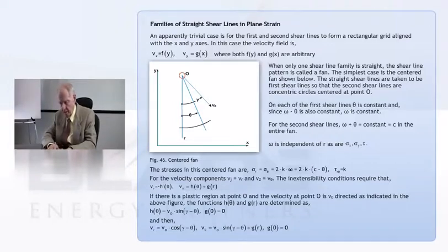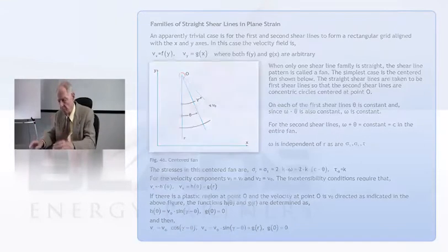And if you look at the line above that, then you stick h of theta into those equations, and g of 0 has to be 0. And then you can come out finally with the last equation on the page, and it gives the velocity field that you can have. It's not unlike the shearing one, except now the circles are sliding on each other.